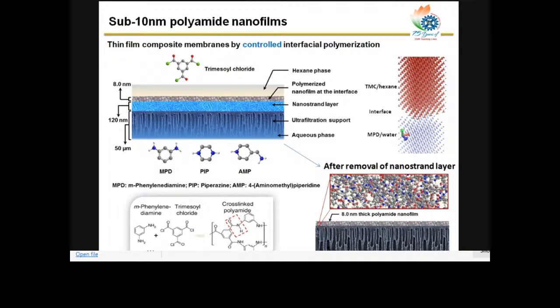If you see this cartoon, we took a support membrane and we impregnated this m-phenylenediamine in the support membrane. We took a nanostrand layer to get a reservoir of the amine compound. And then we make an interfacial polymerization on top of the nanostrand layer to get a polyamide layer from m-phenylenediamine and trimesoyl chloride. So if you see the chemical structure here, we can happily make a very thin, highly networked cross-linked structure of polyamide. And after removing the nanostrand layer, you can get a very thin 8 nanometer thick polyamide nanofilm.